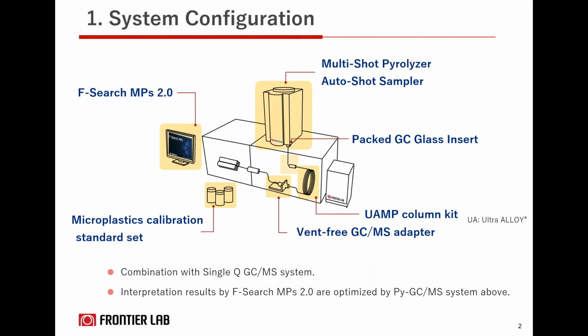So Pyrolysis-GC enables a direct analysis of solid and liquid samples and can be applied to different types of samples that are even insoluble due to the large molecules and cross-linked structure. As you could see from this slide, we've developed a Pyrolysis-GC system that is optimized for the analysis of microplastic in environmental samples. With this special data analysis software, which is called the F-search MP 2.0, even if you don't have experience in polymer analysis, you could easily use this technique. The analysis procedure, including the identification or the quantification, is automated using the AutoShot sampler, and the results can be obtained in less than 1 hour for each sample.